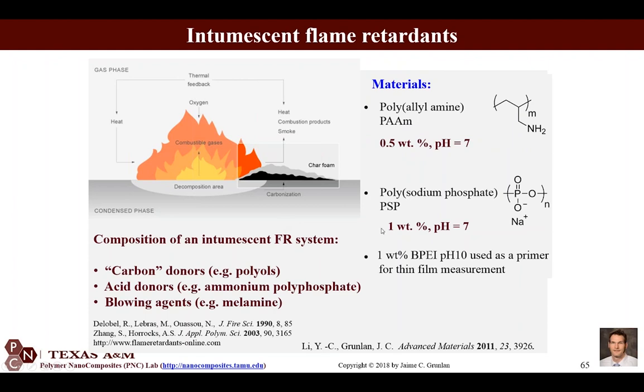And so what we did is we layered this nitrogen-rich polyallylamine with this phosphate-rich polysodium phosphate. And then we put this on cotton fabric, and the cotton itself was a carbon donor, the phosphate's an acid donor, and the blowing agent, quote unquote, that bubbles things up is the nitrogen-rich polyallylamine.